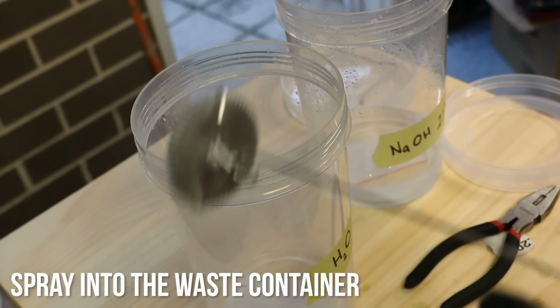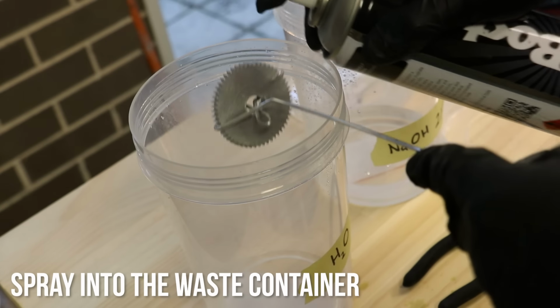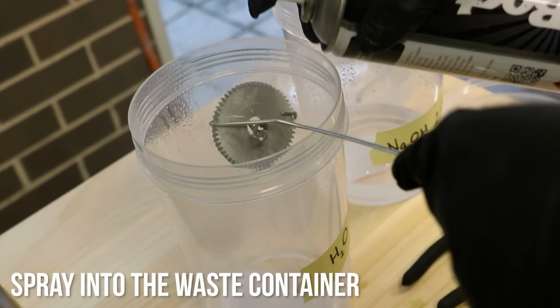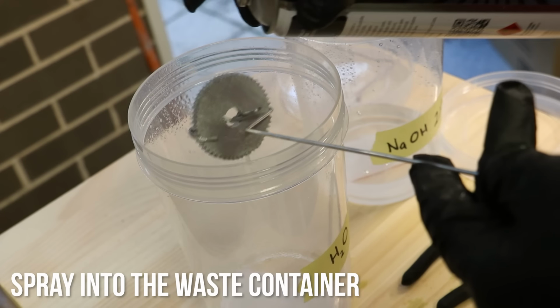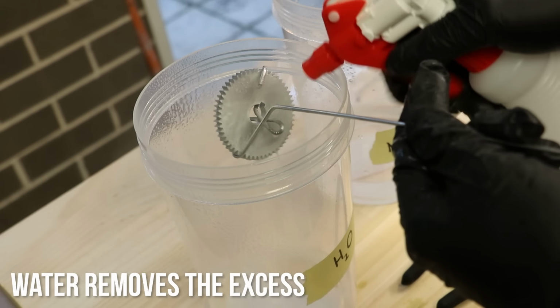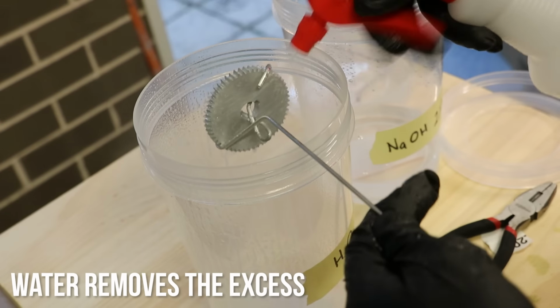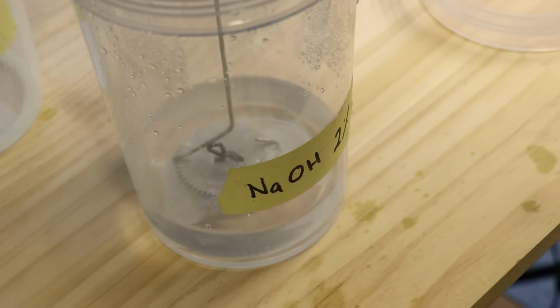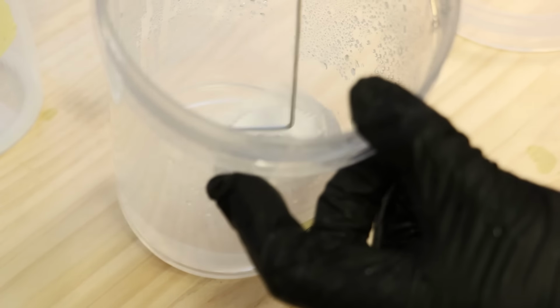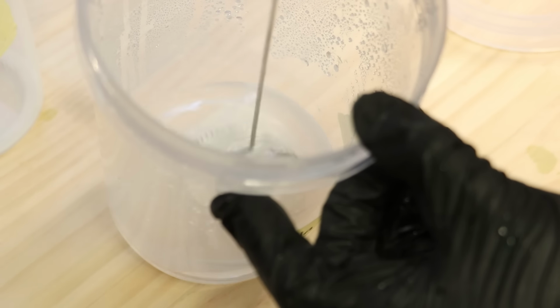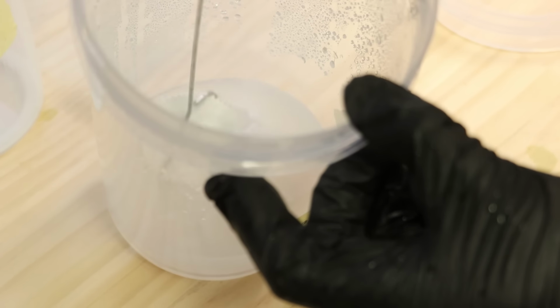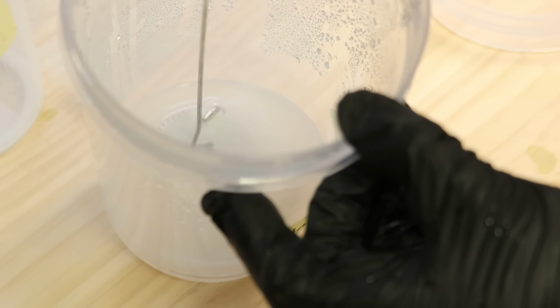And once we're happy with it, we'll then give it its final spray of brake parts cleaner, which is probably the most powerful solvent that I have here. It'll then get a spray of distilled water before being put in the sodium hydroxide bath. And depending on the part size and the concentration, it only needs about 30 seconds there before you can remove it and then give it its final spray of distilled water.